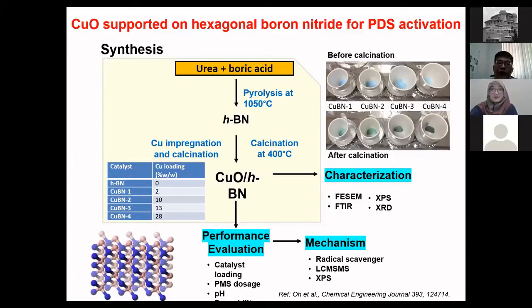But if you support it on hexagonal boron nitride, so hexagonal boron nitride is another very important material that people start to look into recently, right? Because it has a very good adsorption property. It is also very chemically and thermally stable. You take this boron nitride, if you calcine it up to 800, 1000 degrees Celsius, it's still there because it's very, very stable. And it's also very resistant to chemical attack. So if it's in the environment where you have a lot of oxidant like peroxydisulfate, this boron nitride can withstand all this oxidation environment.